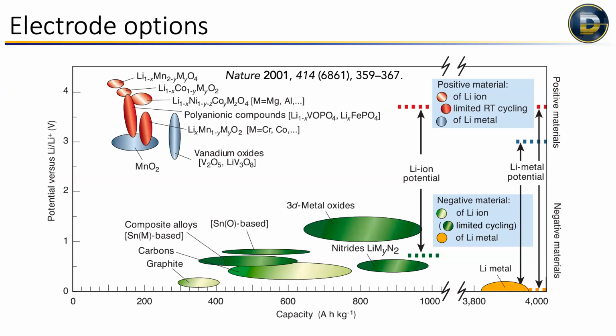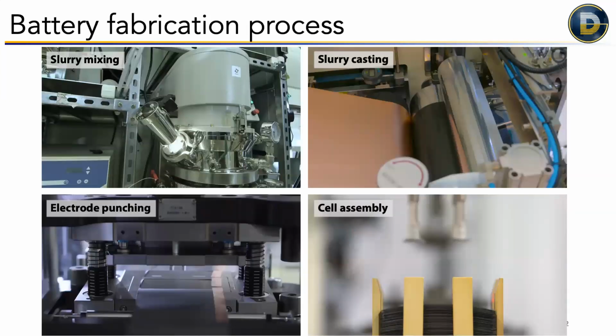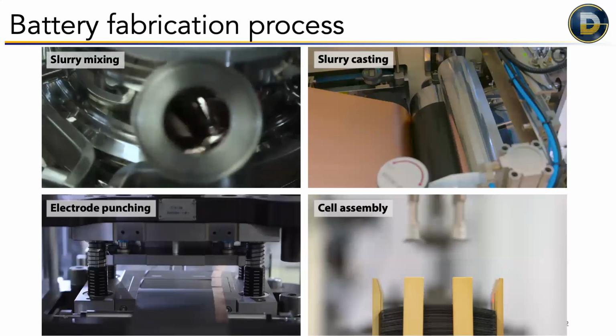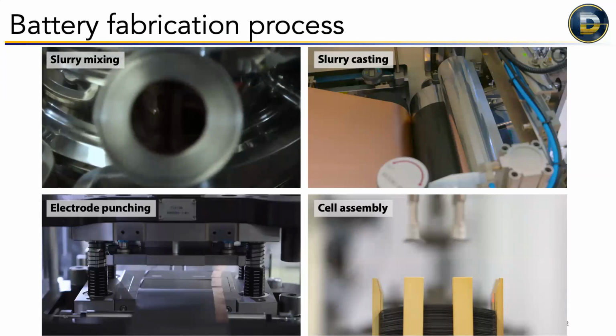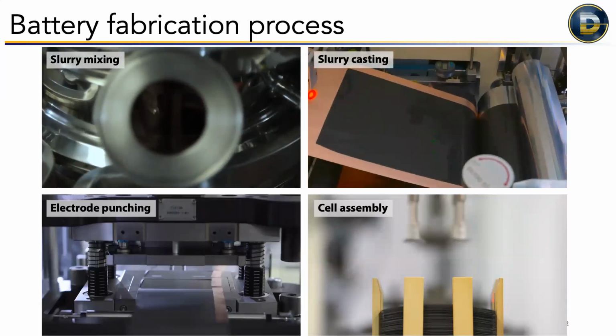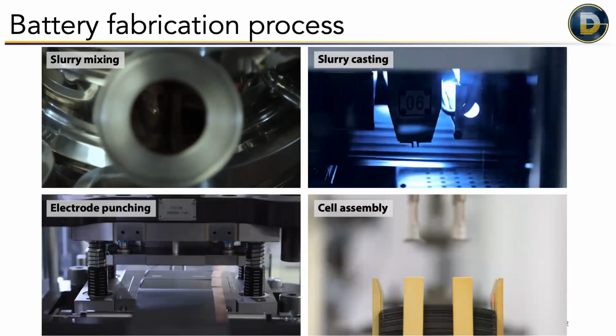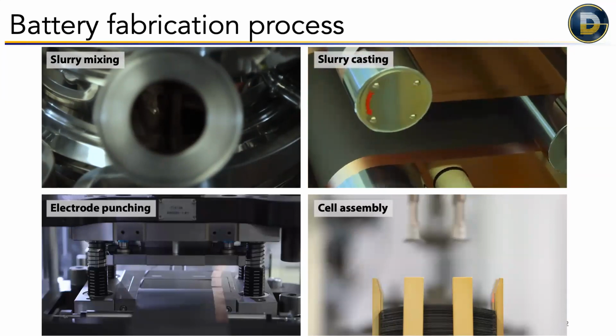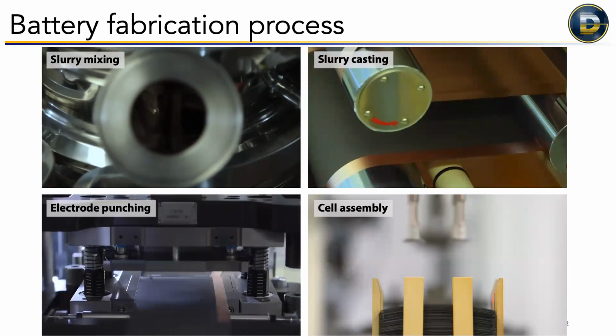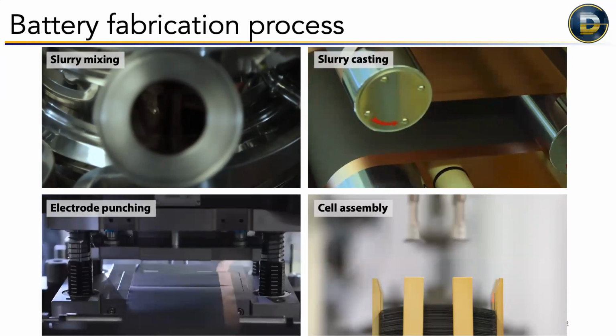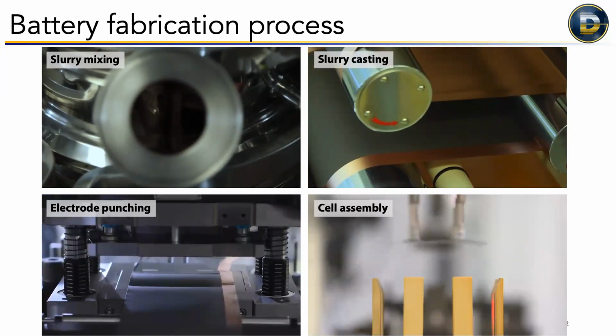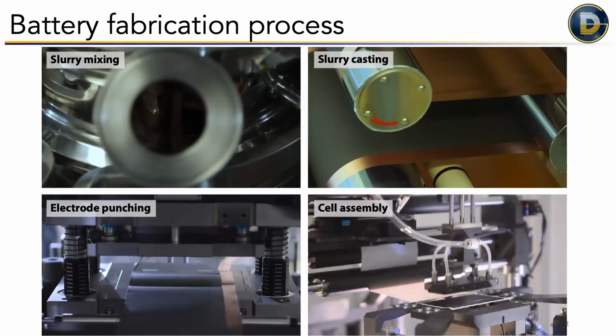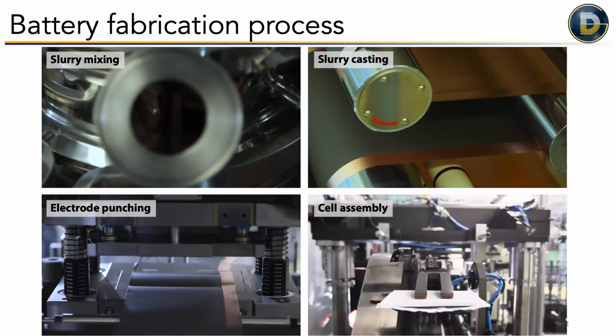So once we've selected these materials, then basically we grind it up into a small powder, and then we mix it in what is basically just a giant KitchenAid mixer here. So you can see that gray stuff in there is the slurry. And then essentially we paint that onto a very thin metal foil. The electrode is about as thick as a strand of human hair, give or take. And then we cut out individual electrodes from that large foil, and then stack those electrodes, anode, cathode, with separator in between so that the electrodes don't touch. And then you put a liquid electrolyte in there, seal it up, and you're good to go.